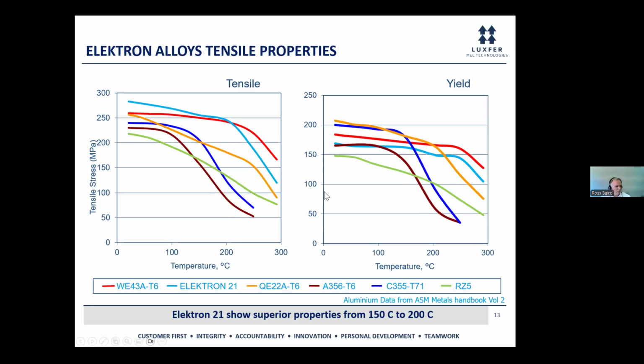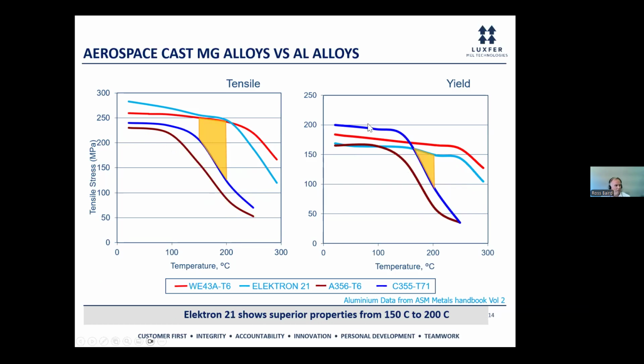If I actually move on to a simpler version of this graph, you'll see that once we're above 150 to 200 degrees Celsius, we now have a magnesium alloy that outperforms the standard aluminium sand cast alloy that we see in a lot of aerospace components. And that is really where the sweet spot is for the applications, at about 150 to 200 degrees Celsius. And there's a similar, not as distinct, but a similar situation with the tensile properties as well for the alloy.